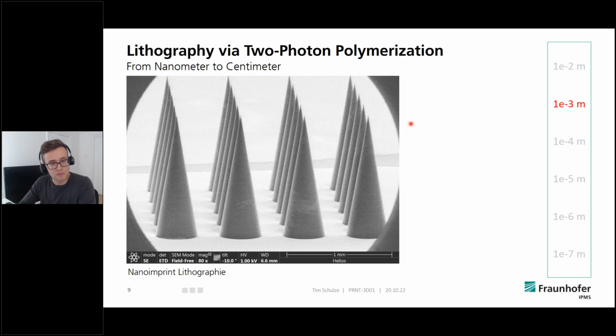This is nano imprinting lithography, and the idea of those little spikes is to use them as some sort of printing substrate, and to push them into the coating or the resist coating of a specific wafer, and to imprint those structures into the resist. And once you do an etching process on those chips later on, we are able to transmit those structures into the chip. And this is also successfully done.